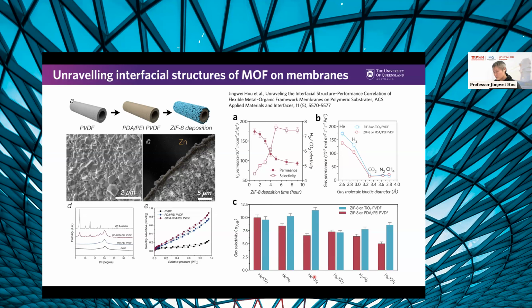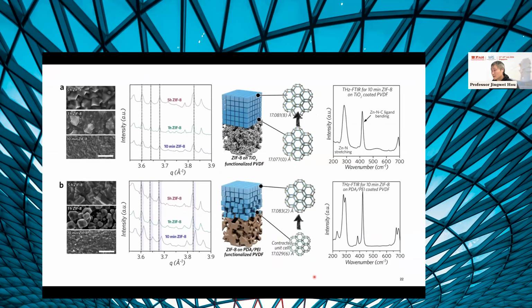That really made us think whether we had done something wrong. But we tested those results multiple times. We still got similar results. So I thought, okay, there must be something different between those two membranes, even though they look very similar from the XRD, from the SEM, from the gas adsorption results. So that's the beginning of another journey.